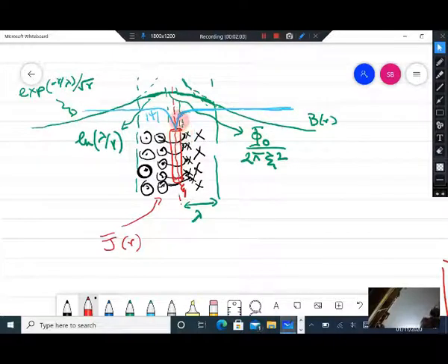Around the vortex there are currents which are circulating, which are actually shielding the magnetic field. When you apply a magnetic field, the magnetic flux inside the vortex core will be present because it is a normal region, but outside it, as it is superconducting, the magnetic field will be shielded out. And so there are screening currents, shown in black, which are circulating around this vortex, which will try to shield the magnetic flux and decay it. It is because of this reason that the magnetic field decays down outside in the superconducting region, and this gives rise to the shielding currents.